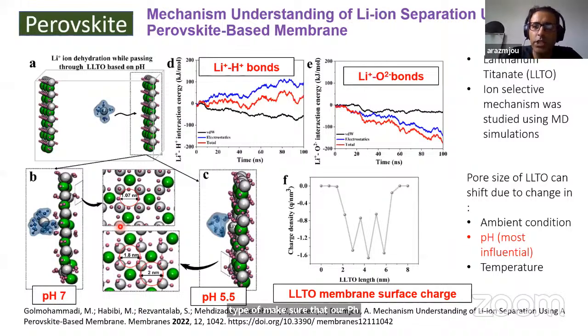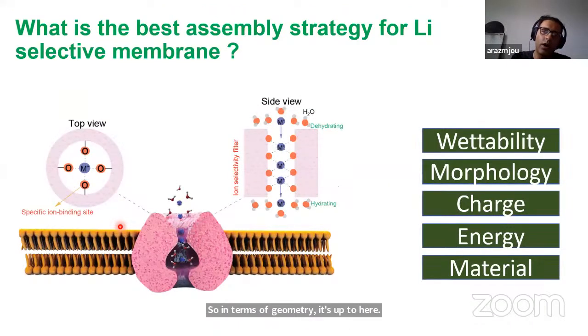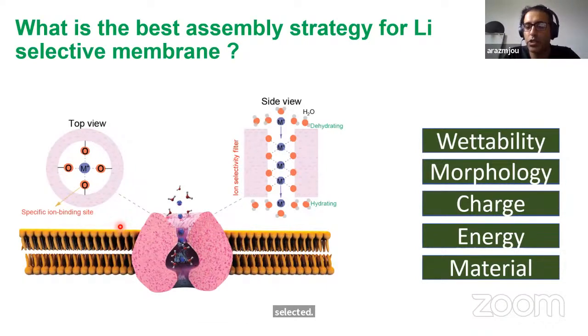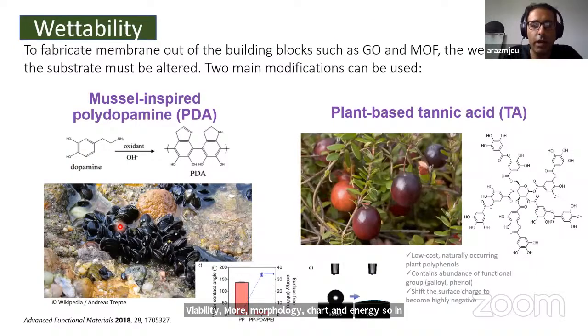So in terms of geometry, up to here I talked about how switching from one building block to another, you can tune the ion selectivity and ion conductivity of your material. There are other parameters you can play around with to make your membrane lithium selective or any sort of ion selective: wettability, morphology, charge, energy, and material. In terms of wettability, what we found is that when we use different types of chemicals, for example, polydopamine or tannic acid, we managed to get different types of lithium selectivity.